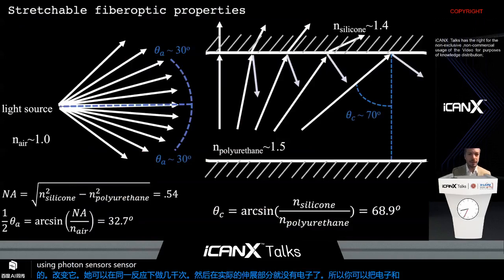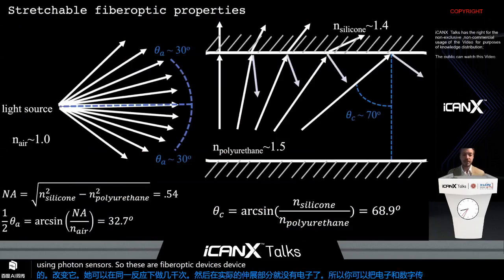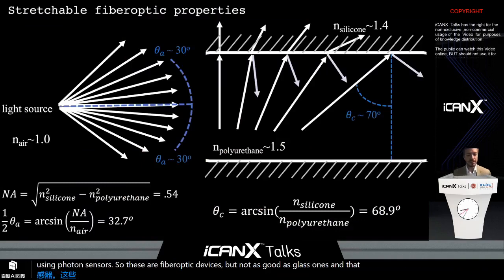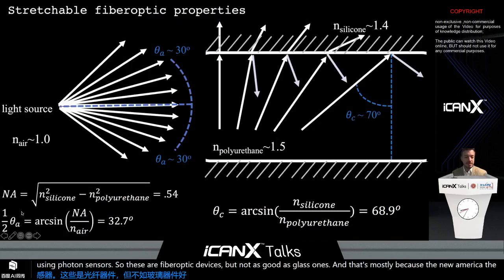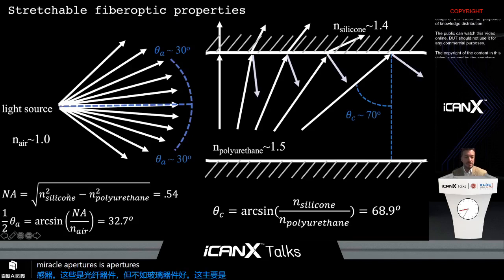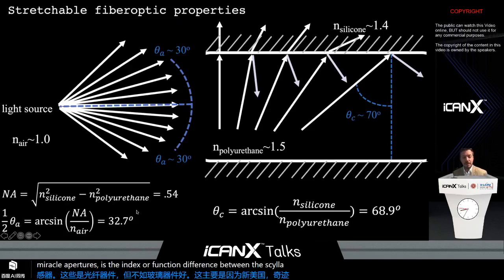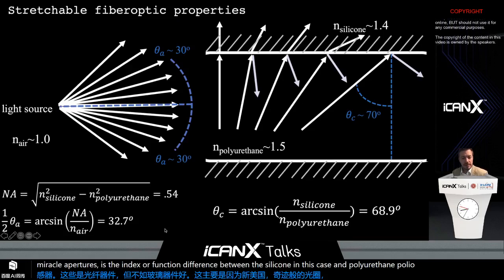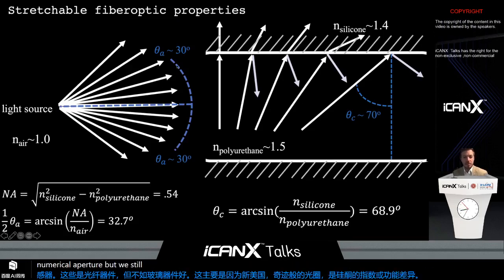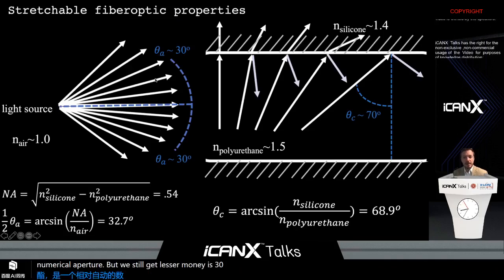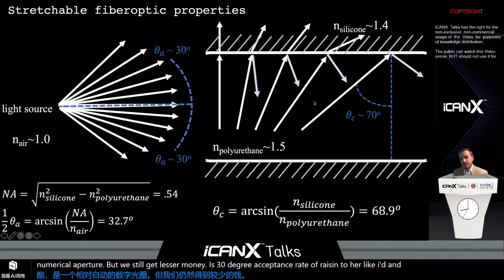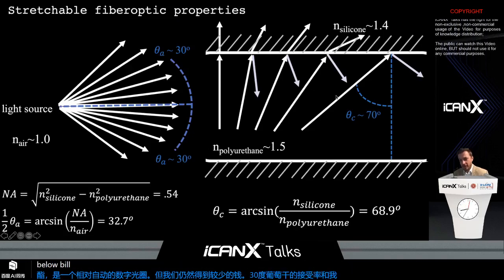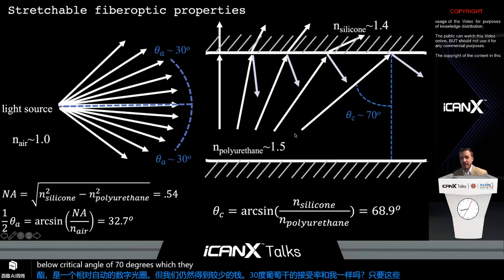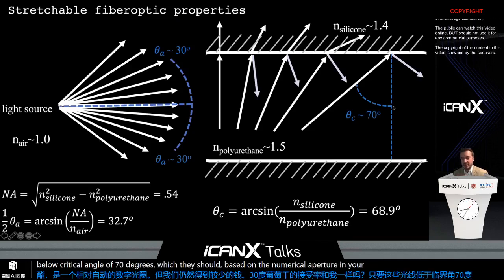These are fiber optic devices. They're not as good as glass ones, and that's mostly because the numerical aperture is smaller. The index of refraction difference between the silicone, in this case, and polyurethane is a relatively low numerical aperture, but we still get plus or minus 30-degree acceptance of rays into our light guide. And as long as these rays stay below a critical angle of 70 degrees, which they should based on the numerical aperture, then they're trapped in this light guide.